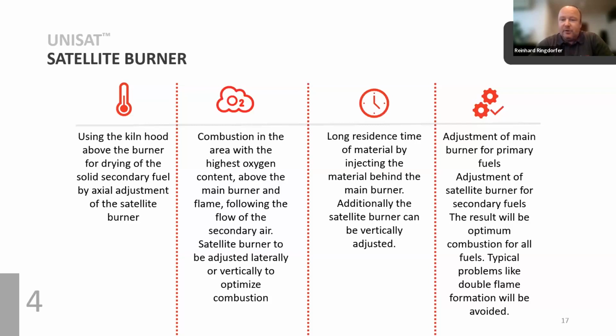We heard before that the satellite burner has been around for, I don't know, 30, 40 years already. I know from cases in the middle or end of the 80s, some plants in Germany started injecting just through a fixed pipe, injecting beside the burner, above the burner. But first of all, a naked pipe tends to burn down in this atmosphere, and the results were not really satisfying. So by, I would say, the end of the 90s, beginning of 2000, when secondary fuel firing started, Unitherm and I think all the other suppliers decided it would be much better to fire the secondary fuel through the burner. A few years back, in 2014, we started to get back to the satellite burner design.